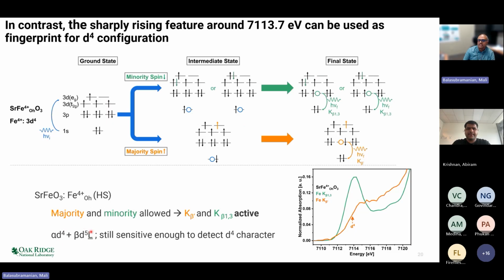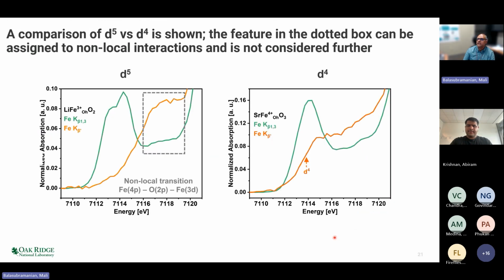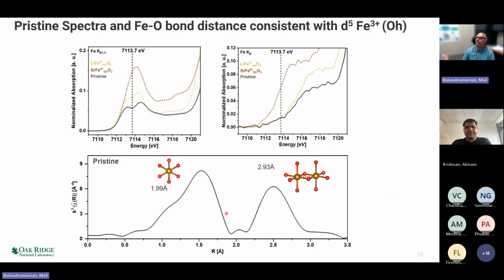But even when this is the situation, this method gives significant sensitivity to this d4 character. So if you ever oxidize an iron 3+ to 4+, you will be able to see that by monitoring this K beta prime feature. So in summary, what you can do is compare. I show here a comparison of 3d5 and 3d4. If you have 3d5, you will have no intensity here in the K beta prime. In the case of 4 plus, you would see significant intensity here in the K beta prime. Okay, so we will use this as a fingerprint to follow